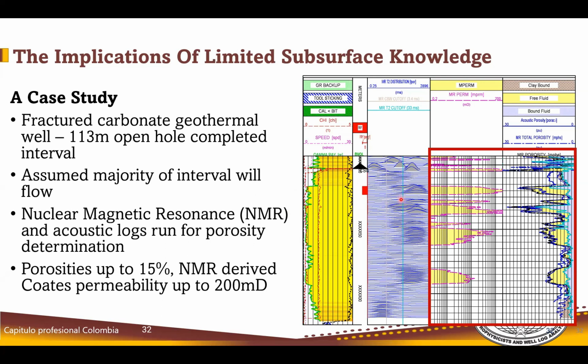For those who are not familiar with NMR data, the easy way to read it is this. You can see a series of peaks here. The position of these peaks from left to right basically represents your pore size, with small pores being represented by peaks on the left, large pores being represented by peaks on the right. The assumption is the larger the pore, the more likely it is to flow. Of course, by looking at your distribution of pore sizes, if you have a lot of large pores and very few small pores, you can make the inference: large pore throats, good permeability.